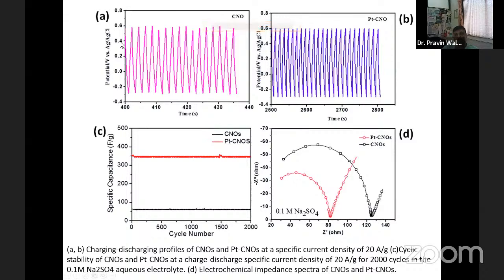Here you see the charge and discharge, with a number of cycles. Every line going up is charging and coming down is discharge. There are more than 10, 15 cycles you can see here. This one shows the bare CNO, and this one shows the platinum decorated CNO.